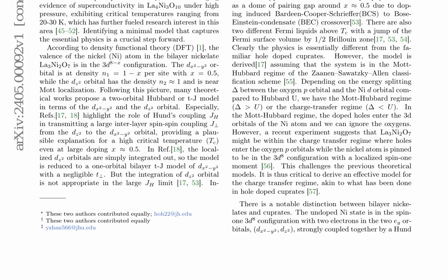For the cases where Np,L,1 equals 1 or Np,L,2 equals 1, the local Hamiltonian reduces to a three-site Hamiltonian, which is solved to obtain the ground state wave functions corresponding to the Zhang-Rice spin-half state. These wave functions are entangled by the three P1, d1, d2 orbitals and are illustrated schematically in Fig. S1. The parameters r and alpha are defined in terms of JK,A and JH, and the wave functions are expressed in terms of these parameters.